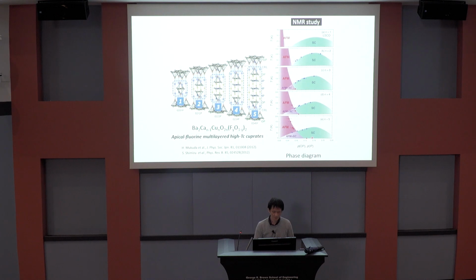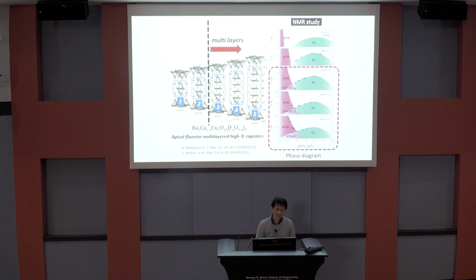If you increase the number of layers, you can expect a cleaner inner layer. So we focus on this apical fluorine multi-layered cuprate. In this system, you can increase the number of carrier layers to 1, 2, 3, 4, 5, even 6. And you can separate two systems: multi-layer, and single and double layer, with clean inner layer versus disordered inner layer.